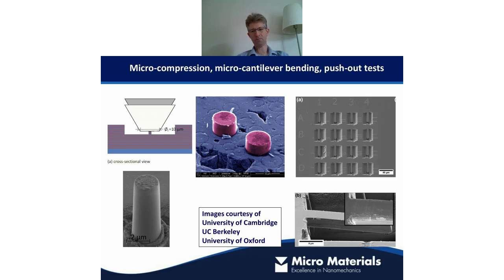They've also machined out cantilevers in this work from Oxford on the right, and then we push on the end of those cantilevers with a Berkovich indenter. At some point you get some elastic property information, and then you may also get some yield, you may get some plasticity, and you may also get some cracking near the root of the cantilever. So again, this is all useful information, allowing people to pull out phase-sensitive mechanical property information.